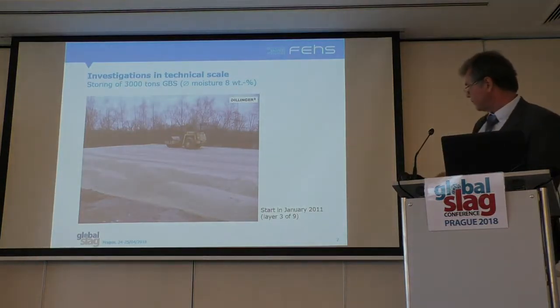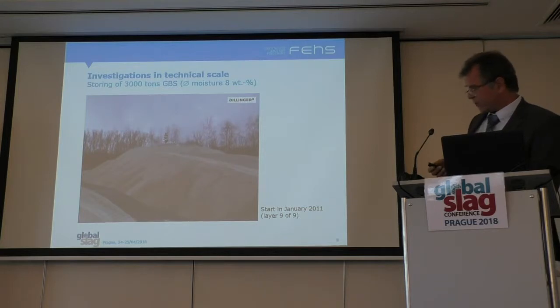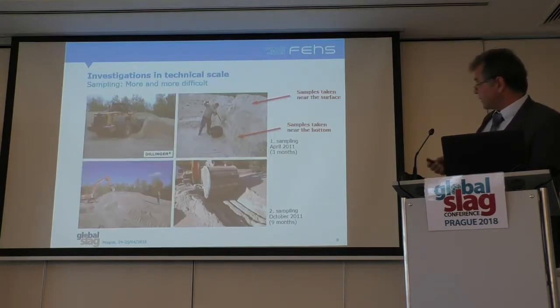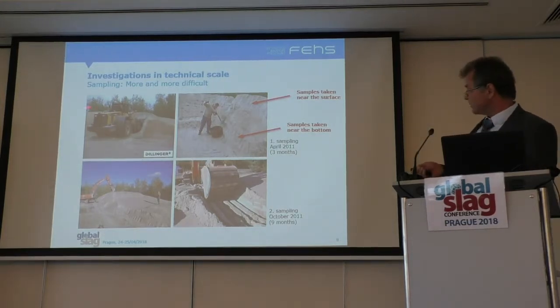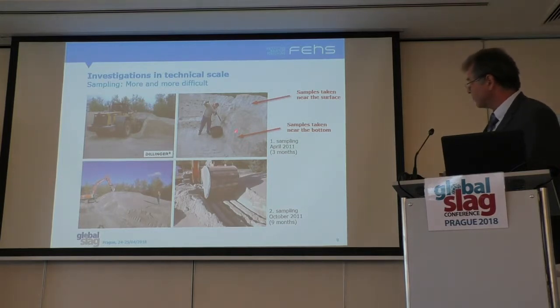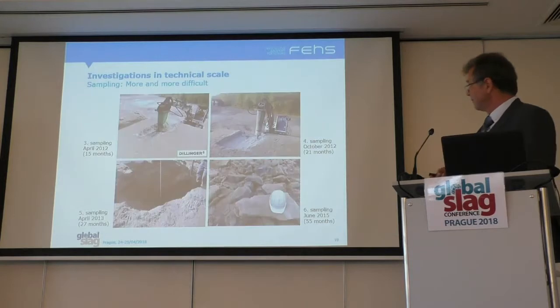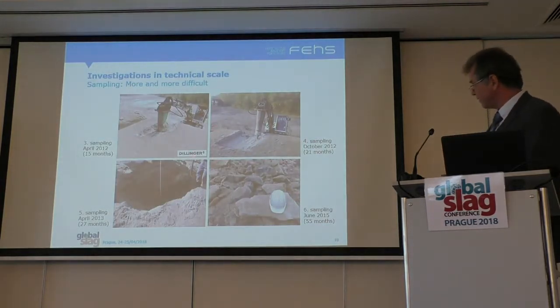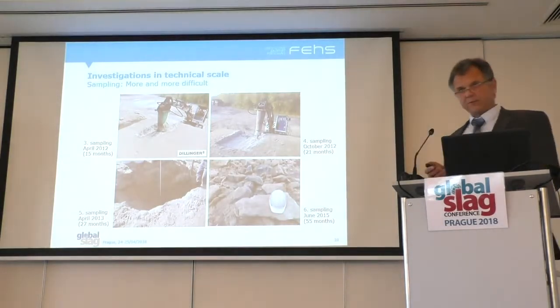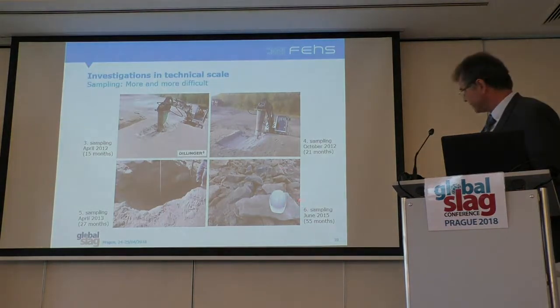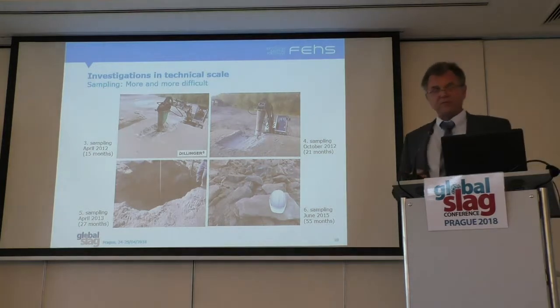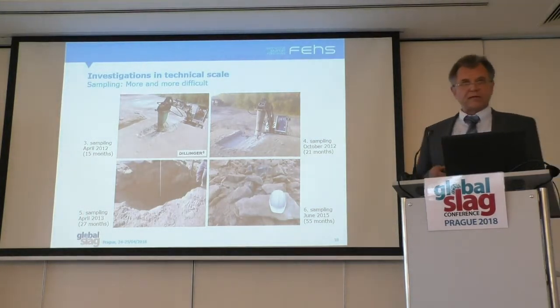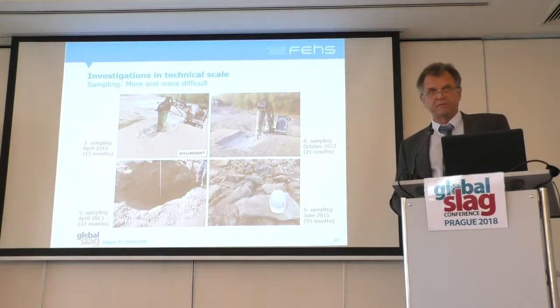We started in January 2011 with creating the stockpile of the GBS, compacting it in different layers. At the end, that was our test stockpile. From time to time, as I mentioned, we took samples. The first time it was easy. After 3 months, my colleague was able to do it by hand. After 9 months, it was not so easy. And after 15 months and later on, you can see it was really a problem to get samples from the bottom of the stockpile. At the end, after 55 months, we got unground GBS without any activation, which looks like fresh broken concrete made with slag cement. Nice blue color.